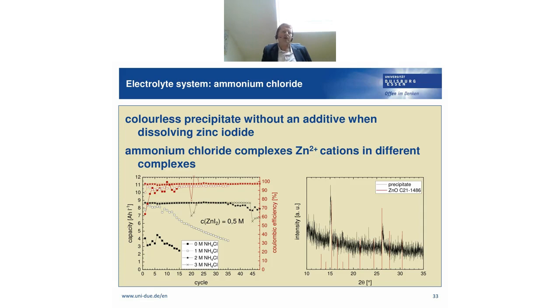So the electrolyte is composed of zinc iodide, and when you try to dissolve zinc iodide, this leads to colorless precipitates. Zinc oxide is formed a little bit, which can be seen here on the right side. So you need an additive to dissolve the zinc oxide properly. And one of these additives is ammonium chloride. It complexes the zinc ions in different complexes and really improves the cycling behavior.